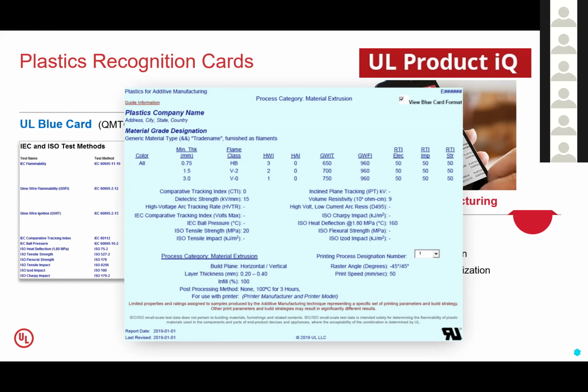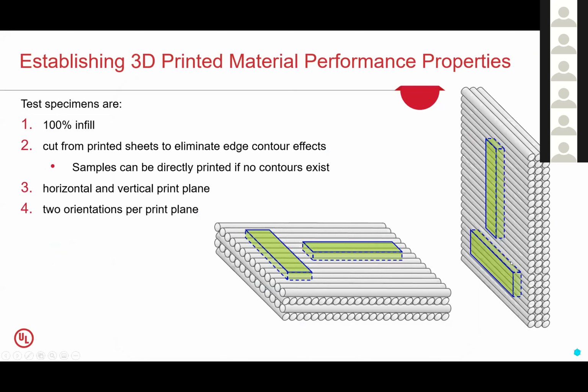It also now opens the opportunity for us to look at a 3D printed product and how to evaluate that 3D printed product for safety performance. A critical aspect when we do this, however, is how do we collect our samples? And this is a really critical difference of what we've seen compared to many other aspects. First, we look at horizontal and vertically printed orientations because we've seen that to be a significant factor. We do look at having samples cut from different angles so that we have an orthogonal set because we do see that as a significant factor on our builds.